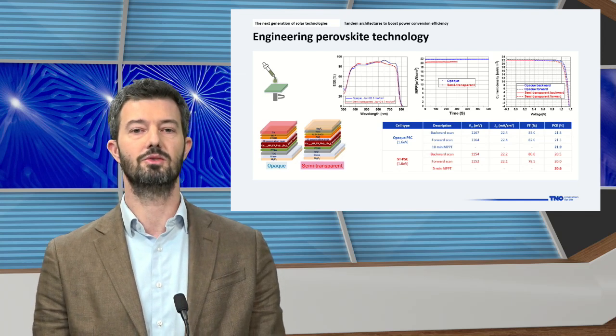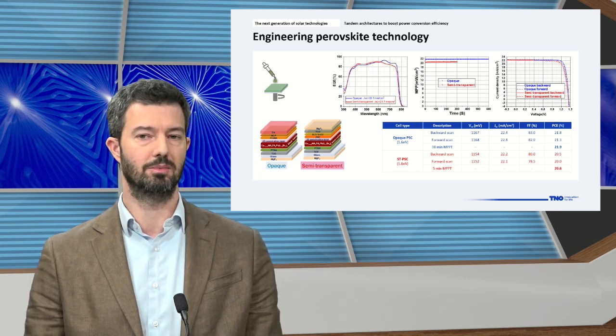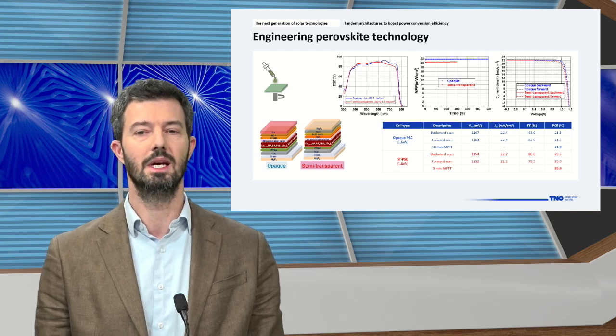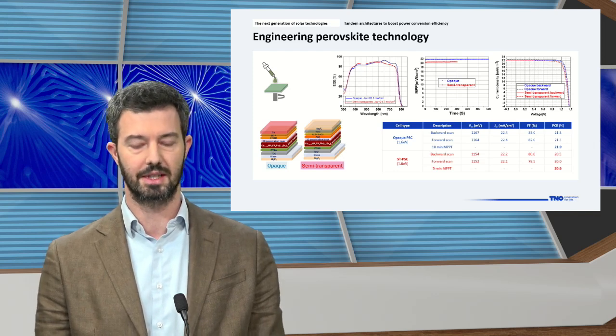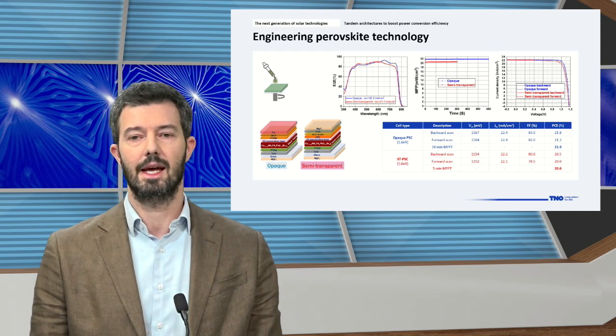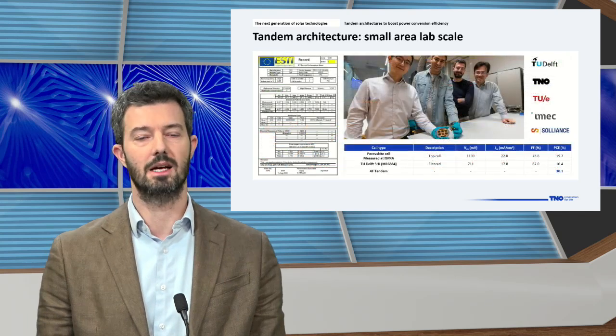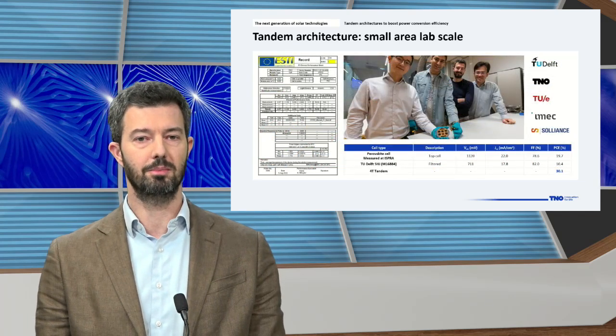And this is a summary of this comparison. For instance, with the opaque device, we can get up to 22%. And when we switch to a semi-transparent device, we get in the range of 21%. So this is one of the top-notch results worldwide. And we wanted to be sure that this is very true, so we also sent it to a third party for certification.